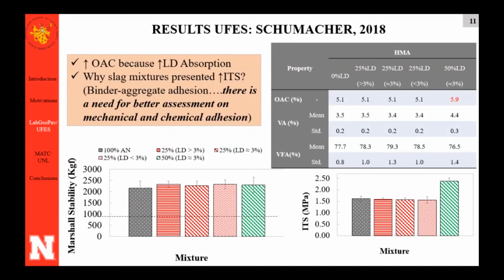We were expecting, since it's a higher strength material, that we could get an increase in this value. But again, it was only 25% replacement, so it did not change. And again, expansion didn't play any role in this parameter. So it was not a problem to use slag as is with a higher level of expansion. And from the indirect tensile strength, we also see that there is no variation, no decrease compared to the natural aggregate. And I saw an increase with 50% on the indirect tensile strength.